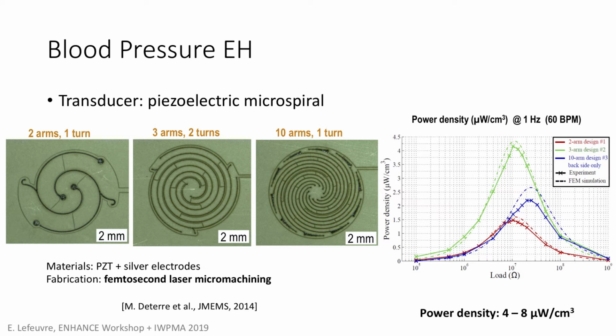So what you can see also on top of each device is that you have some cuts here. The cuts are not across the PZT, just the cut of the electrodes, because we connected some electrodes to positive voltage and other electrodes to negative voltage, to sum the negative ones and the positive ones separately, not to cancel all the charge of the device. And all along the arms, not visible here, we have very small tracks, also micro machined by laser, to connect the electrodes with each other. So it's a very nice system, which is not really standard micro machining, but a nice one.